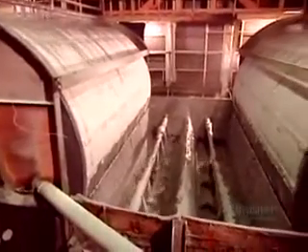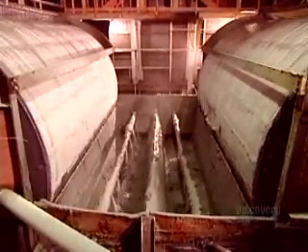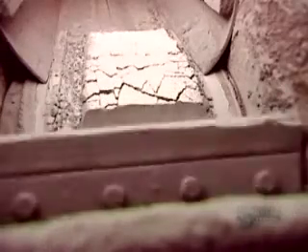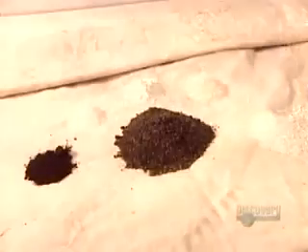The oxygen sets off a chemical reaction between the cyanide and the gold trapped in the ore, triggering the gold to dissolve and leach into the surrounding water. Drum filters then separate the water from the solids. This water now joins the water that was separated earlier. They pour in zinc powder to solidify the dissolved gold and form pieces containing both zinc and gold.